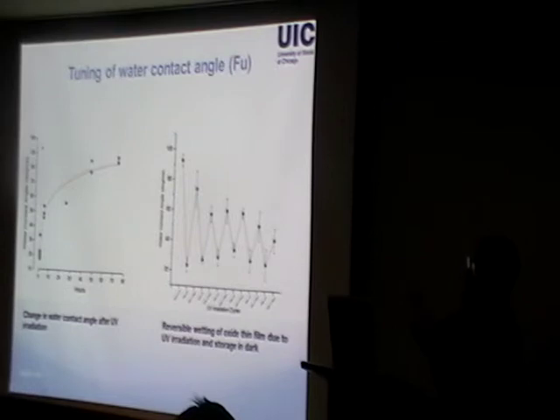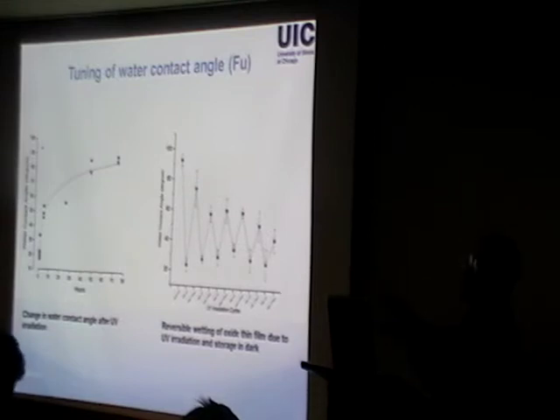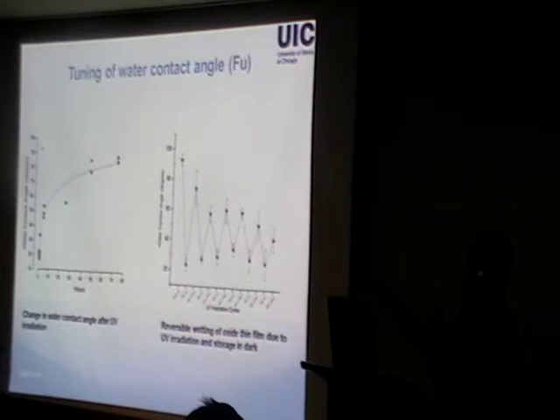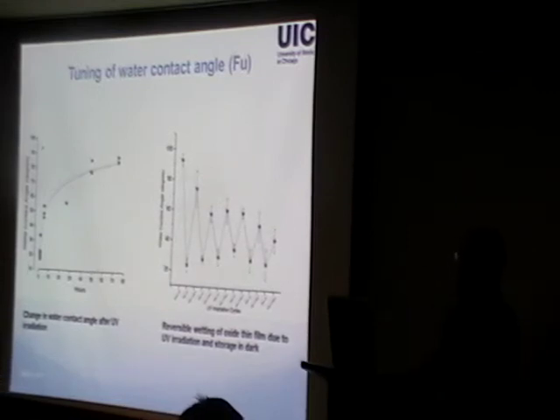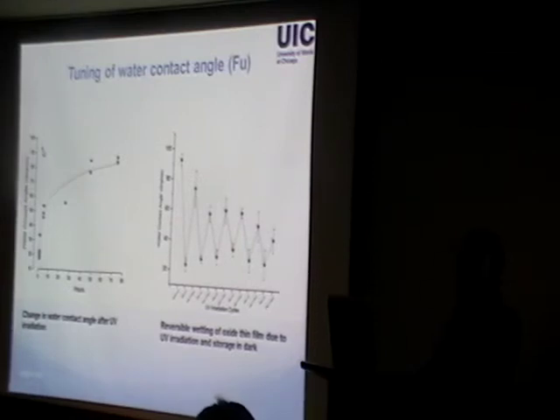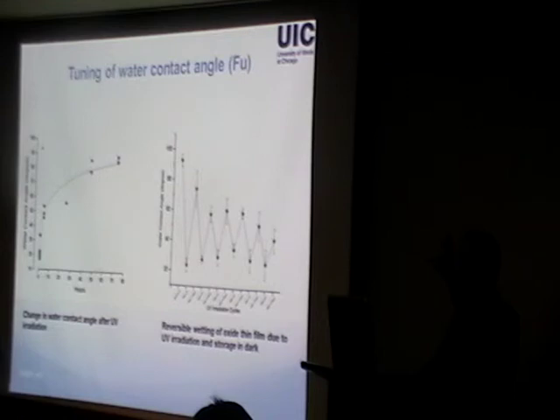Okay, the previous slide I showed you is also fairly new data, but it's been suggested before that this material is hydrophobic. Now Fu is the first person suggesting that we can reversibly tune the wetting of this material. So what are we looking at here? We see water contact angle versus time, measured in hours. The first data point is before shining the UV light, and then immediately after shining the UV light, you measure the contact angle again. You can see the water contact angle is really, really low. And then after some time, the contact angle starts to increase until it saturates around 80 degrees, okay?